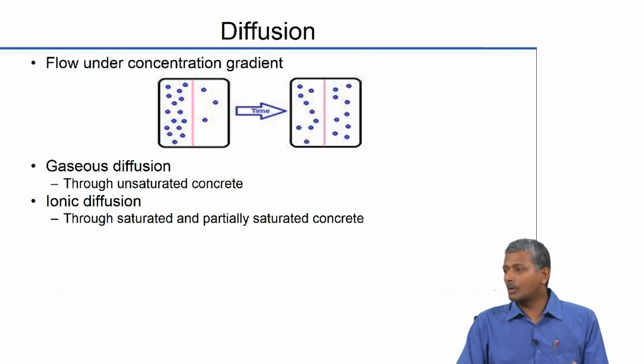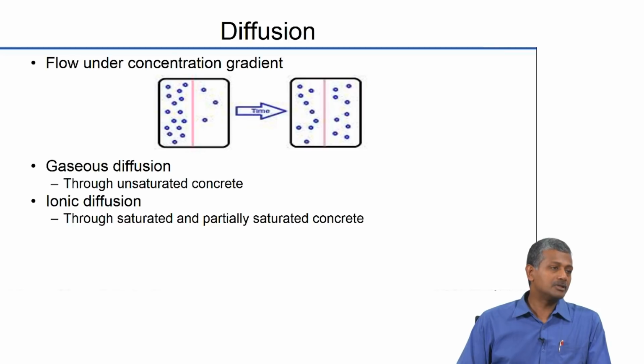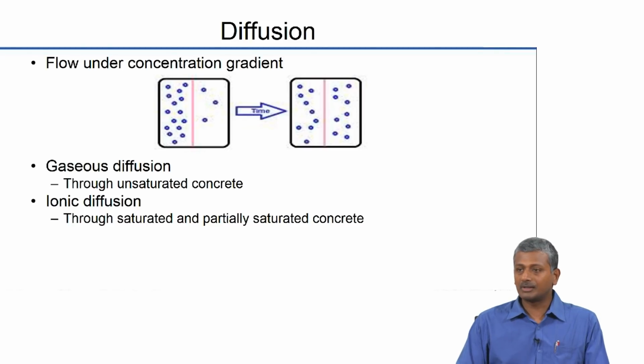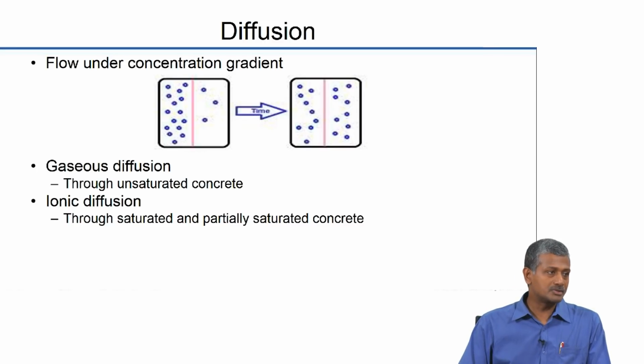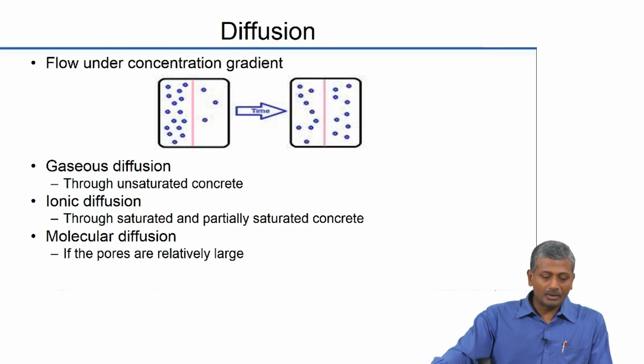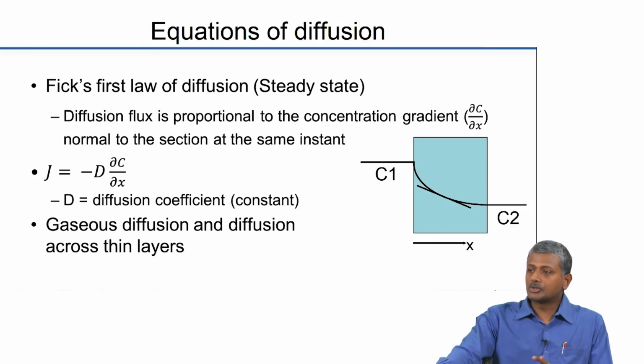So we are talking about chloride induced corrosion, where chloride ions are diffusing from the external environment into the concrete. And this happens primarily in locations like underwater or where you have a lot of moisture available in the atmosphere to carry these chlorides inside. Whereas when we talk about carbonation, we essentially look at conditions for the concrete that are mostly dry, in which case the carbon dioxide penetration can happen over a long distance into the concrete, okay. So when we talk about molecular diffusion like water, pores have to be relatively large to accommodate these molecules to penetrate. Now, we talked also about two different cases.